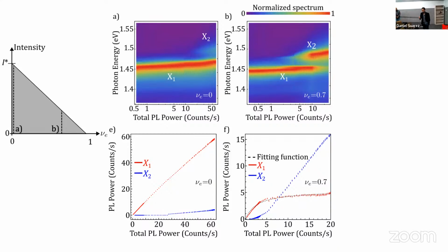Okay, so the first comment is U is the on-site interaction. So that is regardless of whether your lattice is bigger or smaller, U is the same, right? Because it only accounts for two particles in the same unit cell. But if that site is larger, no, because the particles in the monolayer TMD are going to be very delocalized. So this localization is not going to take place. So this Moiré lattice is actually a confining potential for the particles. So we are magnifying U by confining the particles more, but we are also suppressing T by making the lattice more separate. So the unit cell is going to be bigger, and then the particles are going to have a harder time tunneling over the lattice. So that's the key point, I think.